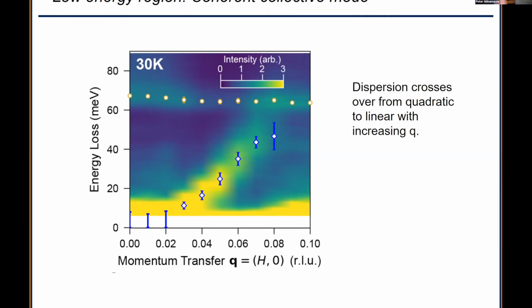Okay, so back to strontium ruthenate. At low energy, there's a mode down there that we didn't expect. This axis is meV, so this is 0 to 80 meV, and this is momentum in reciprocal lattice units. So it's at a quite small momentum scale, something like 0.02 to 0.08 reciprocal lattice units. A reciprocal lattice unit is just the inverse of it, and that's the wavelength in lattice parameters. So we saw this gapless mode.